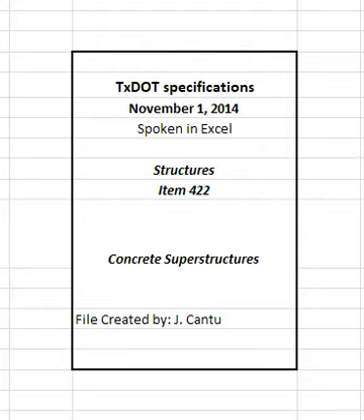Start placement at the lowest end on profile grades greater than 1.5%. At the contractor's option, attach a pan drag and either a carpet or burlap drag to the screed assembly to float and provide surface microtexture in one operation. Adjust the contact pressure of the pan drag to smooth high spots and fill any depressions left by the screed. Adjust the weight or position of the carpet or burlap drag to produce a smooth sandy microtexture without blemishes, marks, or scratches deeper than 1/16 inches. Fill screed rail support holes and holes from the engineer's depth checks for slab thickness and reinforcing cover with concrete, and finish them to match the rest of the slab.